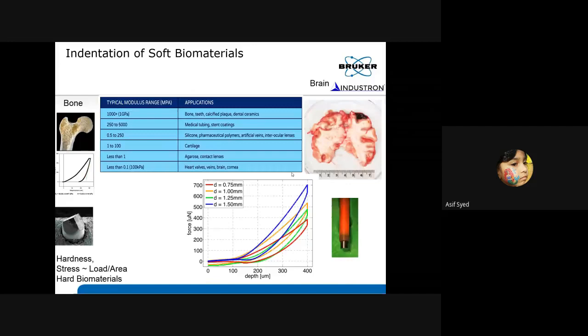So one thing is, when it comes to studying soft material, readily what people do is, instead of using a sharp probe, they use very flat-ended big probes. These probes are like a millimeter in size. This is a flat-end probe, basically a steel pin cut and polished to have a flat surface. So in those experiments, the vertical resolution can still be nanometer, but you lose the lateral resolution because now the surface area is much bigger.